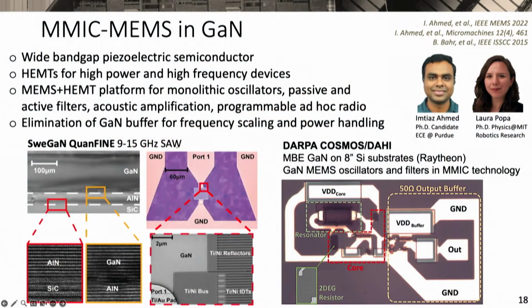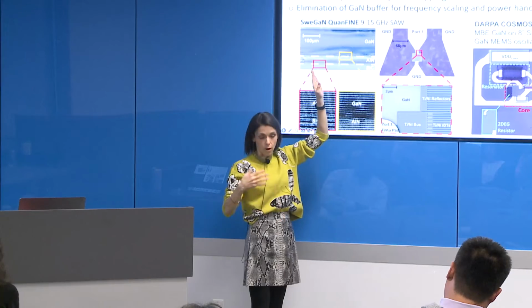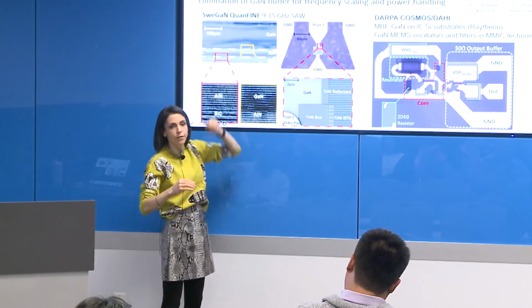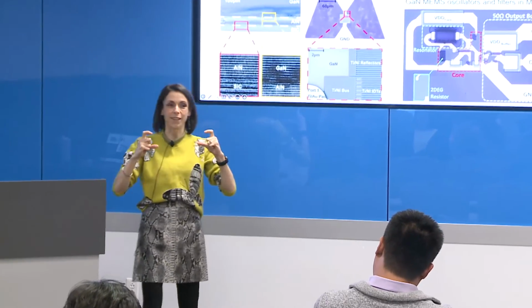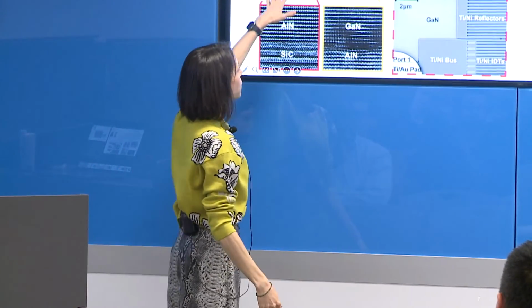So leveraging HEMT technology, right? That's typically used for RF, for high power applications, but now building in MEMS capability into it. We have since been working with companies like SweGaN. They're based in Sweden, but have a beautiful platform where they have this epitaxial gallium nitride on silicon carbide that's basically buffer free. So they make a really thin GaN that's got a beautiful atomic transition to the GaN. They do that for RF and for high power applications, because that buffer is a thermal insulator. It's got all these awful dislocations that prevent thermal conductivity down into the silicon carbide and out of the chip. And so they work a lot to get that thinned down.